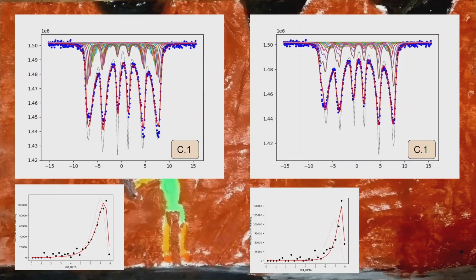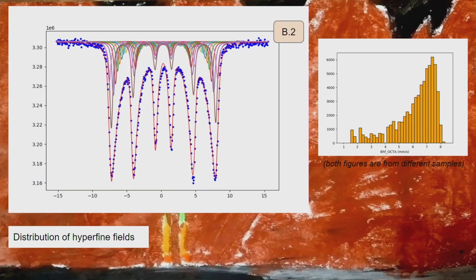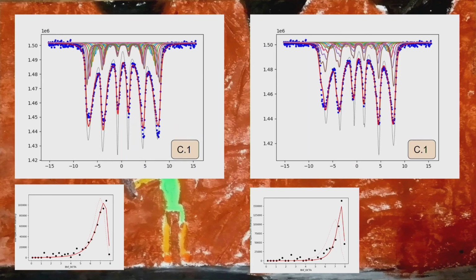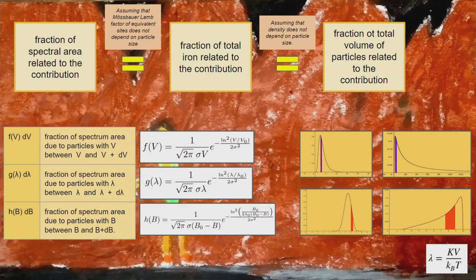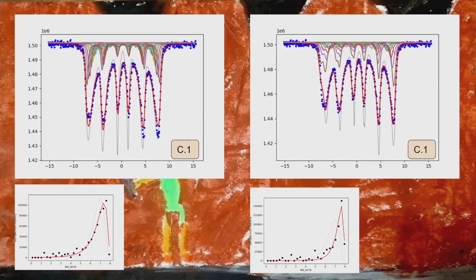And to take the mixture, we have to make a fit with the two models. Each one of these models, on my laptop, takes around 2 hours, each one. And the last one also. So it was very difficult to think that it was possible to fit two distributions of two different sites distributed in different ways. So we decided to assume that the distribution of size is log-normal.